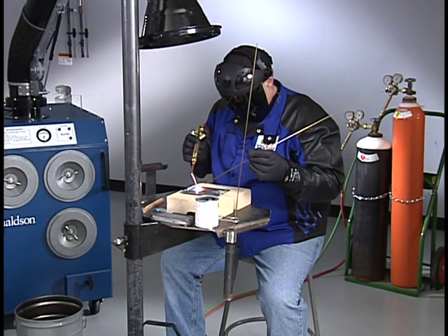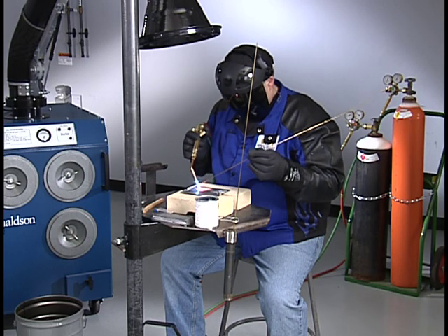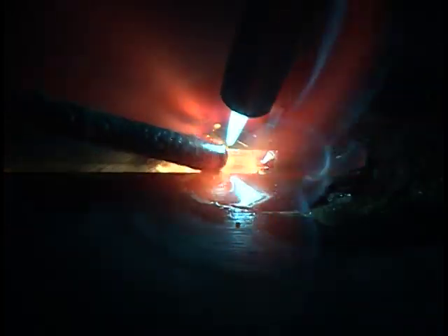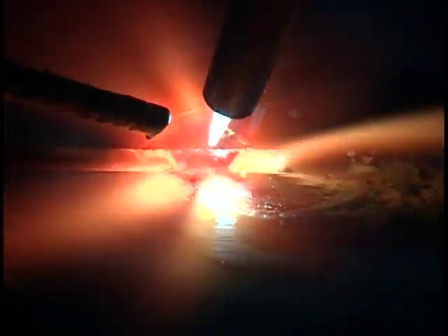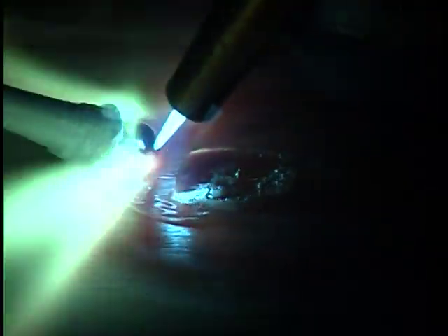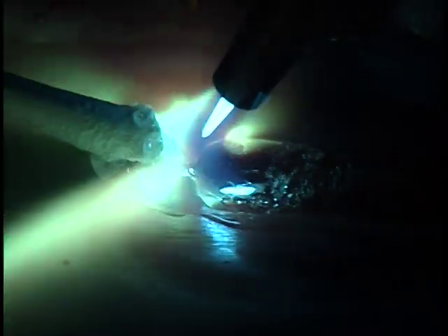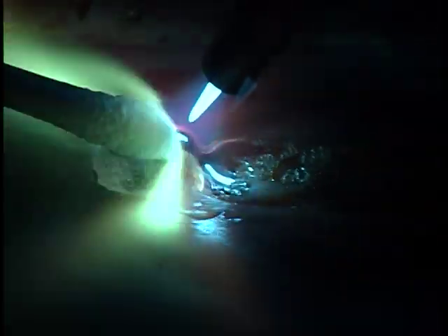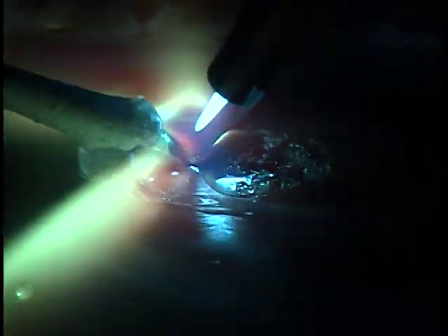If you need to stop welding, withdraw the filler metal and then gradually move the flame away from the puddle. Traveling too slowly or not using enough of a push travel angle increases the heat on the puddle, which may result in too wide a braze weld or melting of the base metal. Using too much of a push travel angle or using too fast a travel speed reduces the heat on the puddle. This results in a narrow weld bead with a weak bond and incomplete penetration.